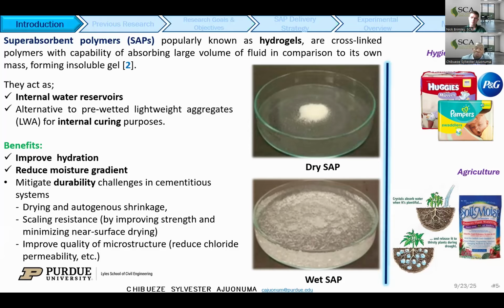It can serve as an internal water reservoir for concrete, and also can be an alternative to the use of pre-wetted aggregates, which is most times difficult in the mix design. Some of the benefits we've talked about: improved hydration, the reduction in moisture gradients, and it mitigates some of the durability challenges in cementitious systems, such as drying and autogenous shrinkage, and scaling resistance. It helps to minimize near-surface drying of the concrete, and most especially improves the quality of the microstructure of the concrete, to end up giving a more durable concrete.